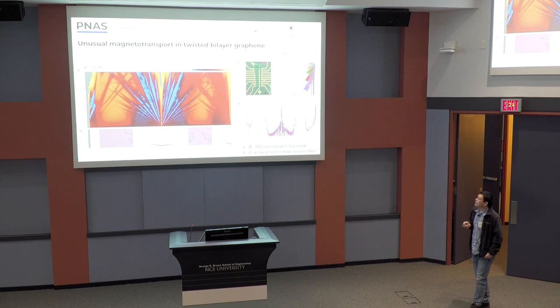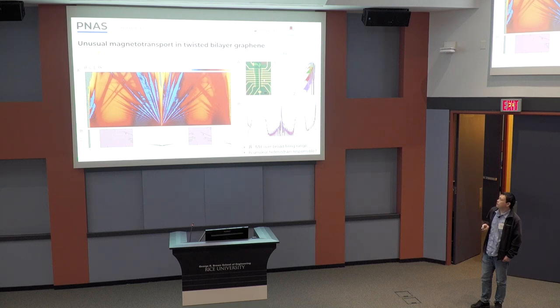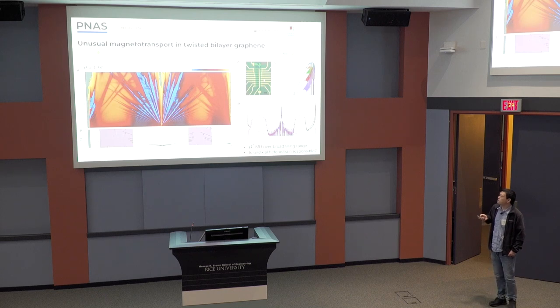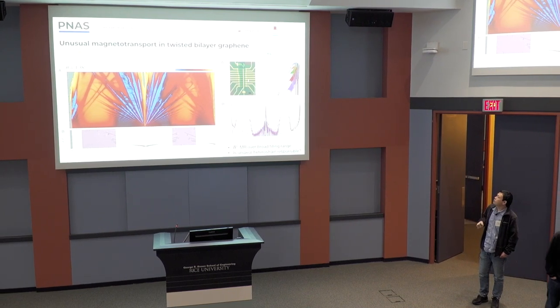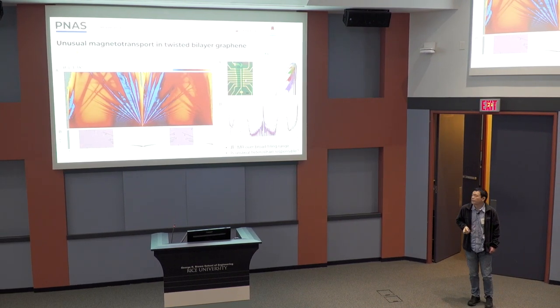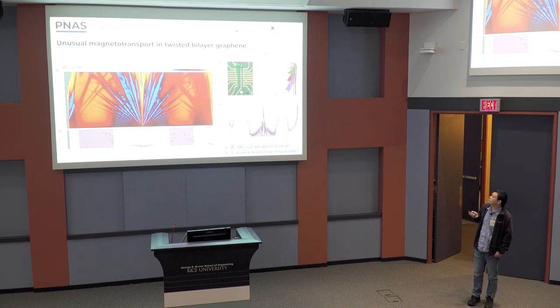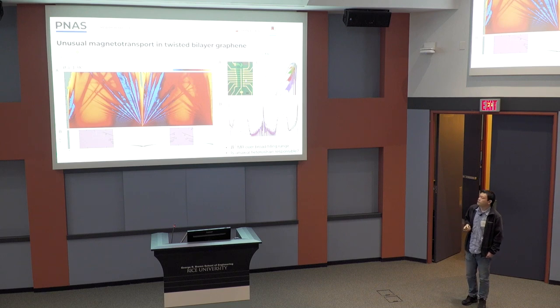What's unusual, however, is that if I look at the low-field magnetotransport, so within this large filling range around the charge neutrality, which is plus minus 2, and then you get this huge enhancement of the magnetoresistance. And doing a line cut, you can see that this black dashed line is b squared. And you can see that spanning over two decades shows this non-saturated magnetotransport behavior.